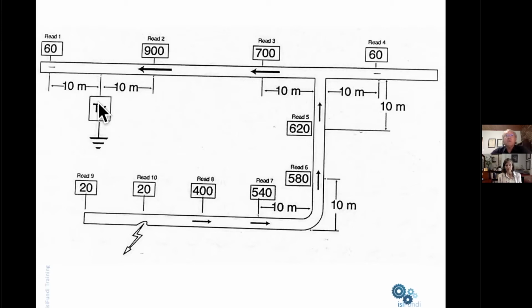So for example, here, the transmitter typically would now be located at a cathodic protection injection point. So you switch the cathodic protection system off and you attach the PCM transmitter in place of the cathodic protection system, possibly even using the cathodic protection ground bed as the earth. That's this point over here. And then you measure the current strength in the pipeline. And you can immediately see if we move out from this transmitter, on the left-hand side, there's very little current. On the right-hand side, the majority of the current. So we know that the current is traveling on the right-hand side of this pipeline.